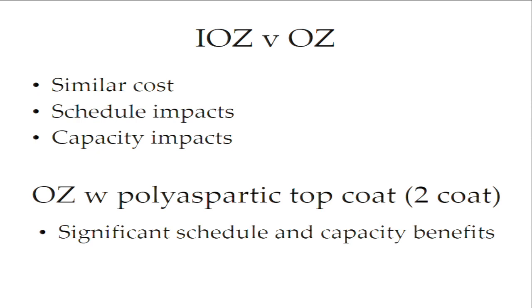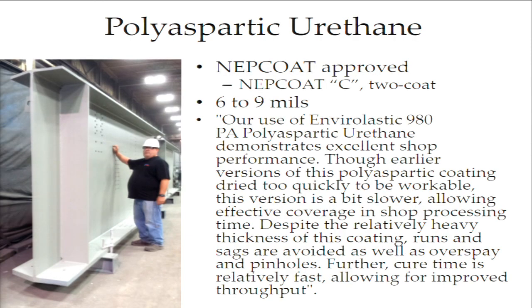And then a little more about that polyaspartic. Jeff was mentioning it. We've done 2 jobs. Here's a picture where we did some tests. The coating has been around for a while. It's used in field application. It wasn't popular with fabricators before because it would dry too fast. And if a paint dries too fast, then we have quality problems. We'll get overspray and we can't build it up effectively. So we had looked at it and others had looked at it and said, no, you know, that's just not doable. But we're looking at this Envirolastic 980, which is a Sherwin-Williams product.